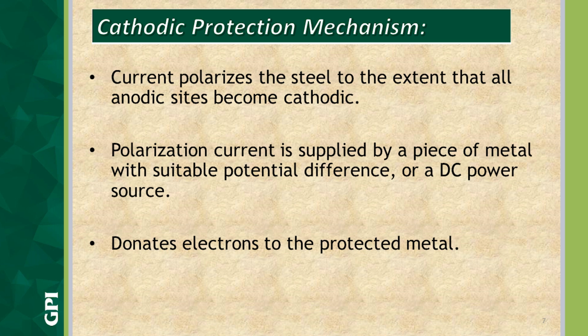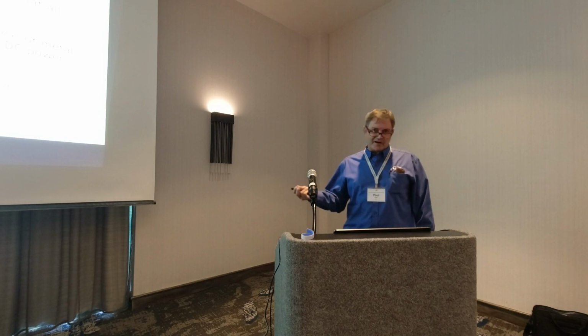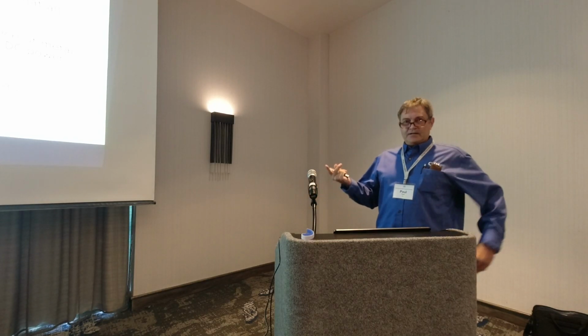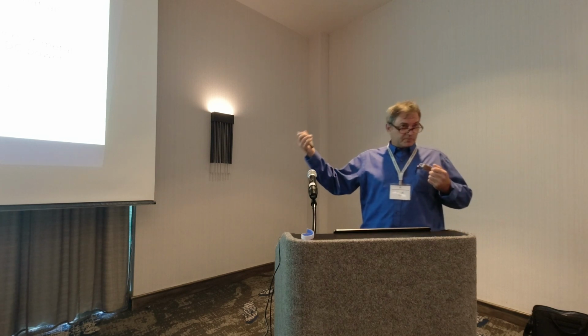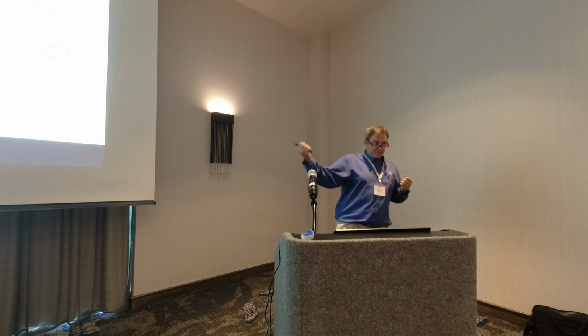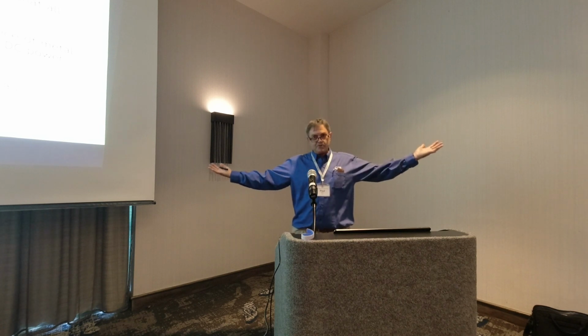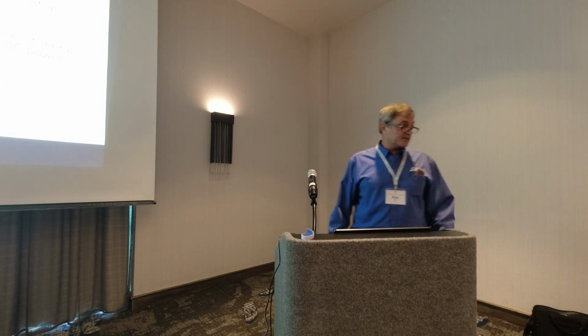So how does this work, in words? What's the cathodic protection mechanism? Well, current polarizes the steel to the extent that all anodic sites become cathodic. That's language right out of the AMPP references and standards. Essentially, corrosion occurs at the anode, right? If you don't have any anodes, you don't have any corrosion. That's basically it.